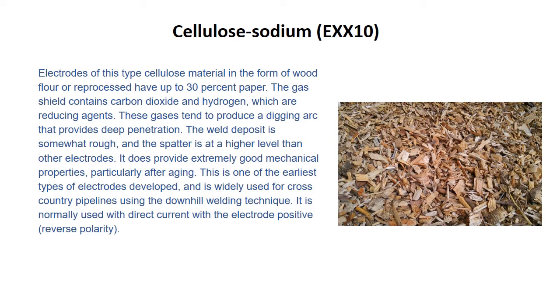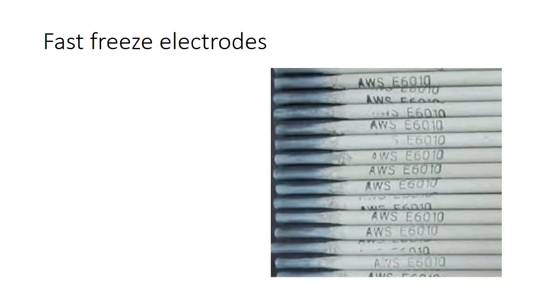Our good friend cellulose, wood chips. These gases tend to produce a digging arc for deep penetration when you burn this stuff. This was one of the earliest type electrodes developed and is widely used for cross-country pipelines using downhill welding technique. It is normally used with direct current, electrode positive, reverse polarity. So that's our good friend 6010. Fast freeze electrode. Here's just a slide with that. Here's what your E6010 looks like.